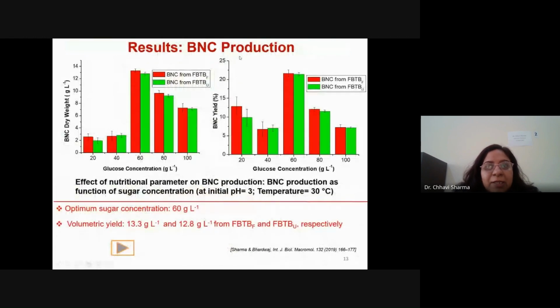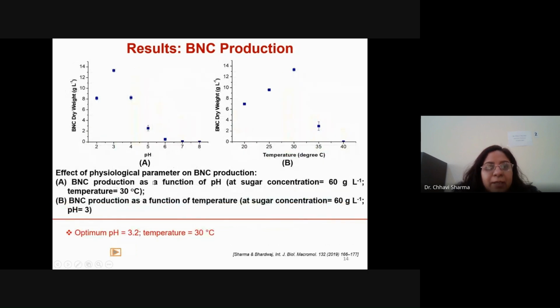So these are some results showing the bacterial nanocellulose production using the fermented black tea broth medium, as well as the used brewed tea, that is the tea part that we used to throw away after making tea. The optimum sugar concentration required is 60 gram per liter, and we obtained a volumetric yield of 13.3 gram per liter and 12.8 gram per liter from the brewed tea and used tea respectively.